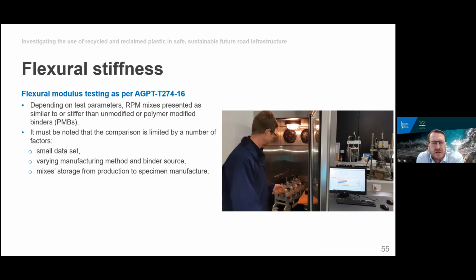So I guess one thing is it was quite difficult to do exact comparisons just due to small data sets or slightly different parameters being used in each of the different research. But generally, the recycled plastic mixes were similar or a bit stiffer than unmodified bitumen asphalt mixes, and similar to the stiffness of the SBS type modified mixes, not quite as stiff as the EVA modified asphalt mixes, but again noted that there's very limited use of that type of asphalt in Australia.